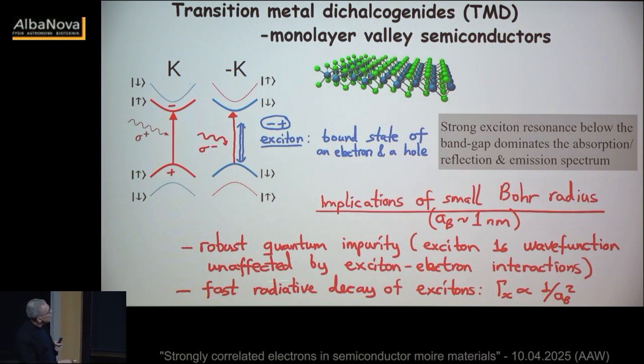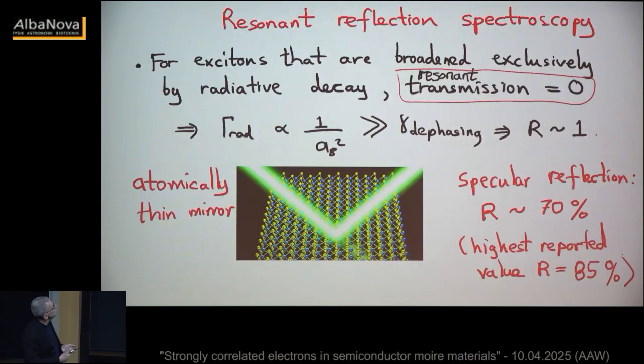Okay. But before that, let me say how we do the measurements. Our standard tool is resonant reflection. We take this material, not standing in free space, but encapsulated between boron nitride to make the surfaces clean. We shine light, and then we look at what gets reflected as a function of frequency. So, the simplest possible spectroscopy, and most of what I show will actually be done with white light.